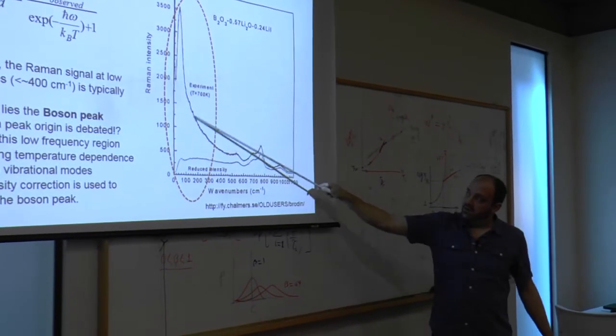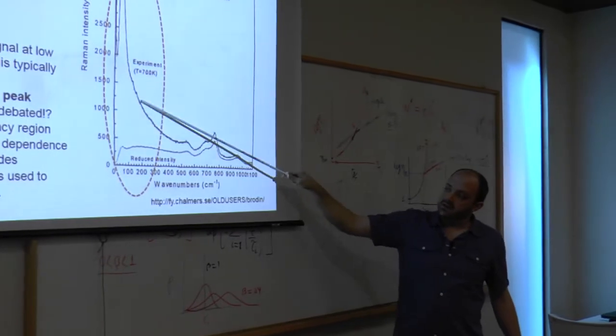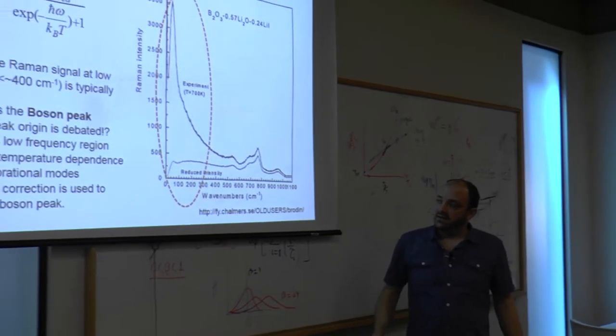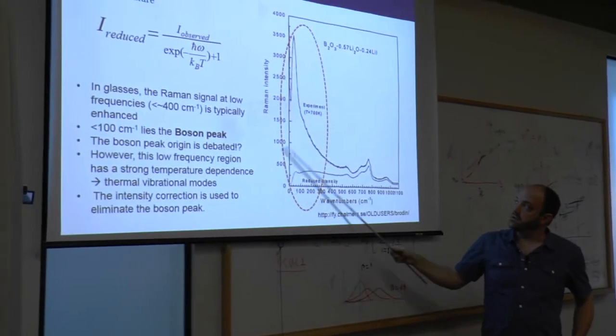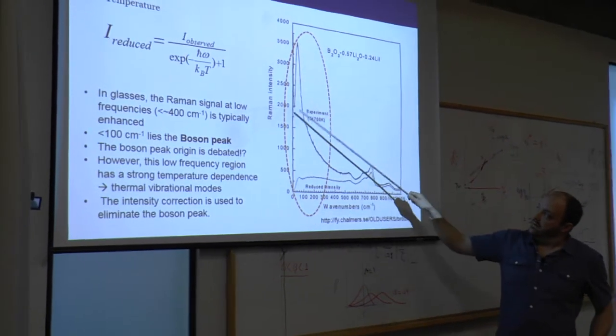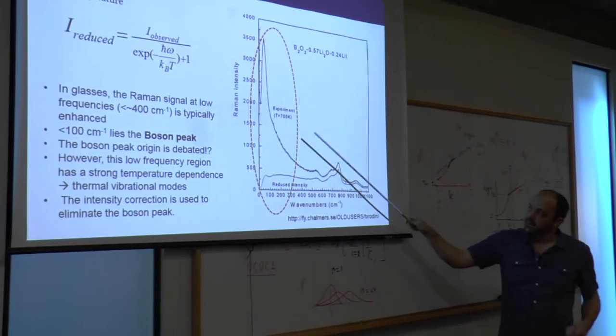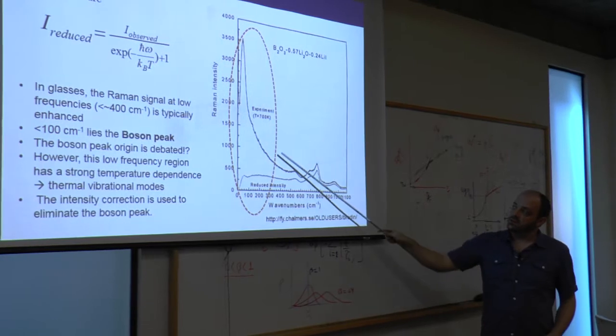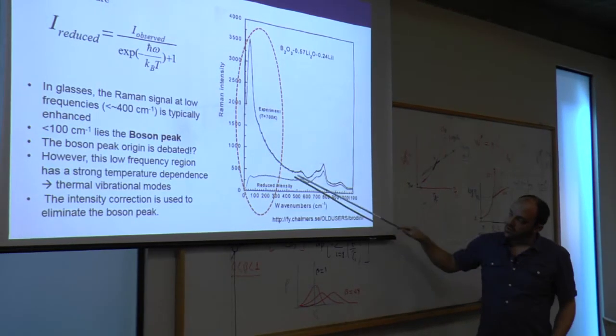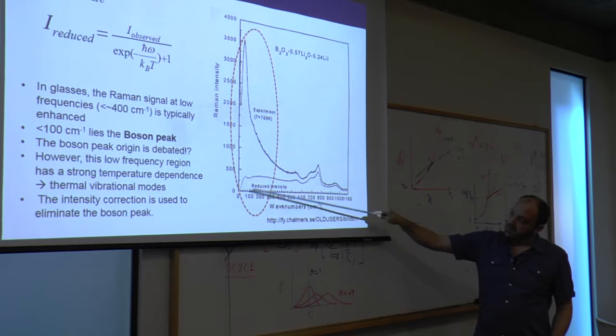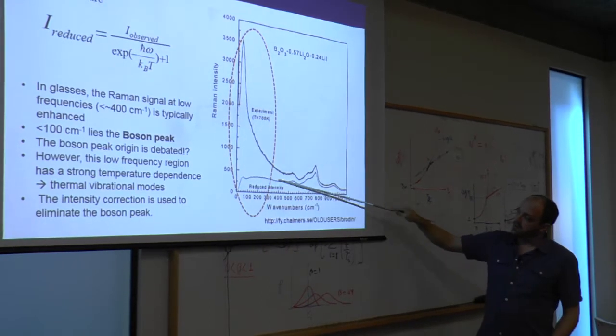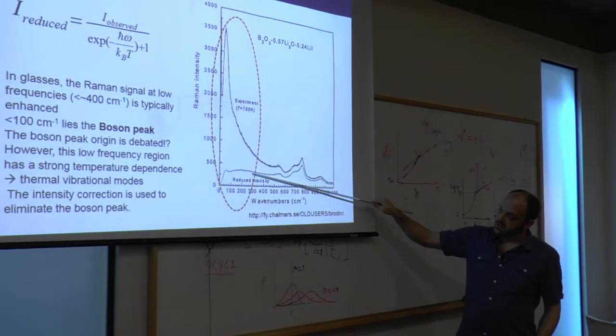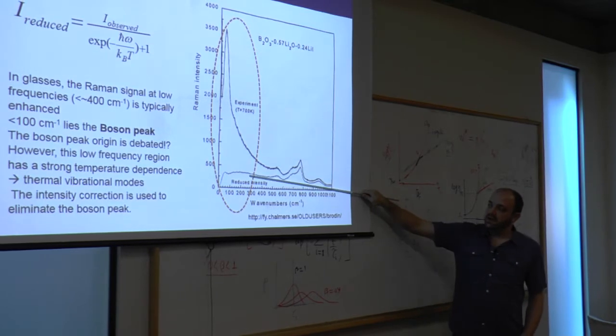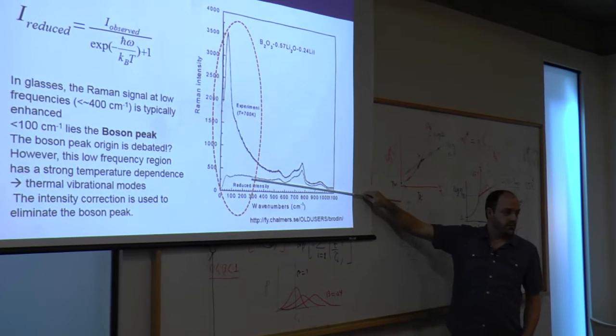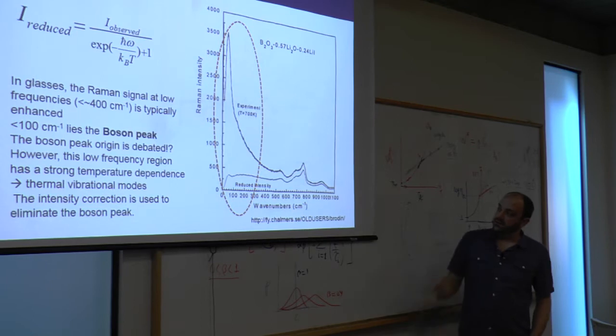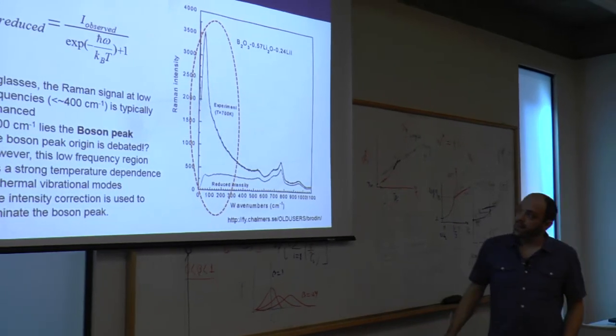So at the beginning, they didn't know where this came from, but they made the observation that it was very sensitive to temperature. Now, the whole point of this correction was originally to get rid of this wild slope, and you can see the corrected spectra, reduced intensity spectra here along the bottom. It looks much nicer to deal with, and you can easily say, hey, there's a straight line somewhere in here to take off the background of the spectra.